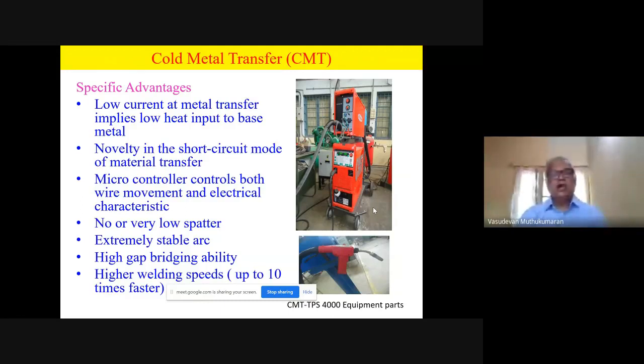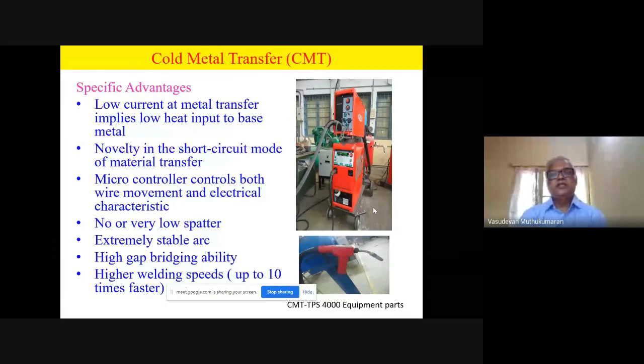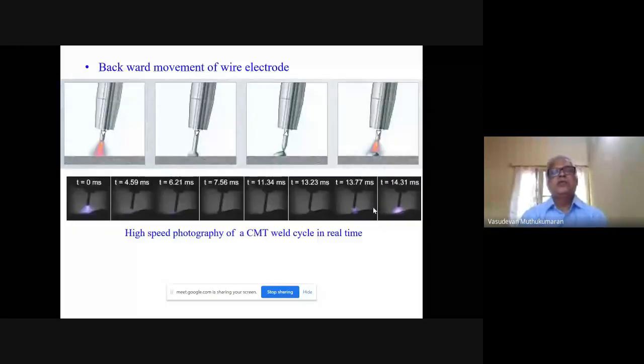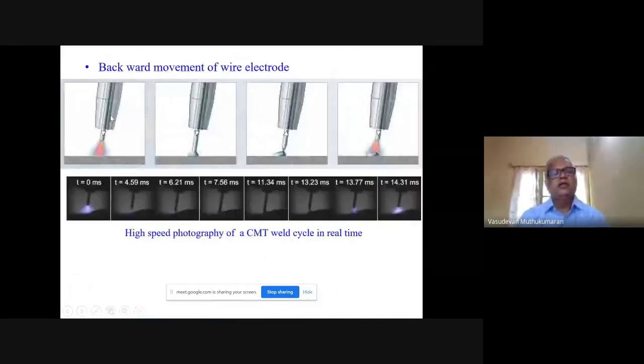This process, I will show how it works, because it's a low heat input process. You can see this is the mechanism. You can see what happens during this MIG welding process. An arc is struck between the filler wire and the material. Once the arc is initiated, the filler wire is moved to touch the weld pool. When the wire touches the weld pool, the arc is extinguished and the current is reduced simultaneously.